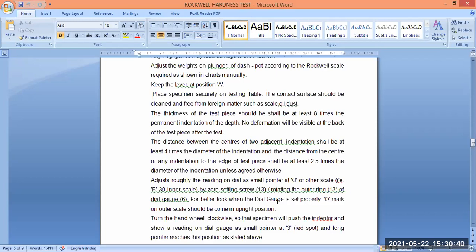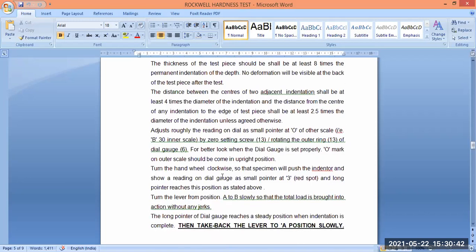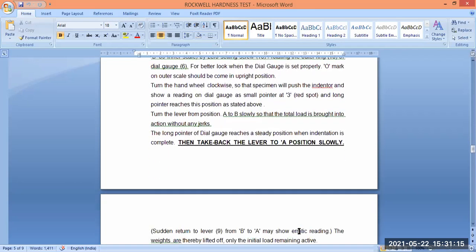Next, we turn the wheel clockwise so that the specimen will push the indenter and show a reading on the dial gauge, with the small pointer at the red spot, until the long pointer reaches its position. Turn the lever from this position slowly so that the load is brought into action without any jar. When the long pointer reaches a steady position, the indentation is complete. Then take the lever back to its position again. After indentation is complete, we keep it there for a few seconds, and release the indenter by moving the rod in the anti-clockwise direction. It will give you the final and accurate reading of the test piece.